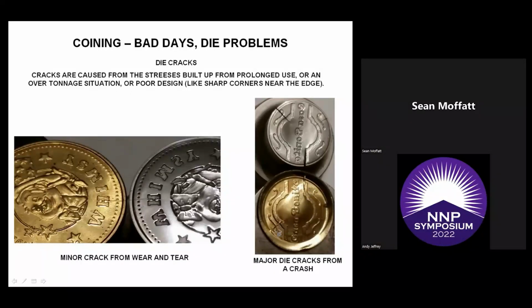And over here, we got this crack translates here. And we got this crack here, which may or may not be visible down there. This die might have cracked after it was done because the remaining stresses will cause a die to crack while it's just sitting around. Those are your die cracks.